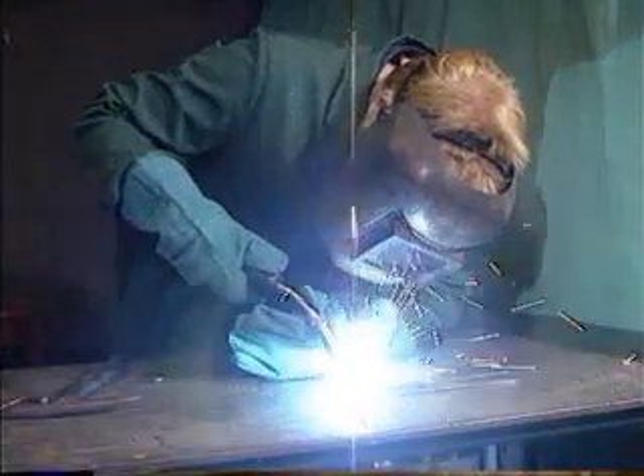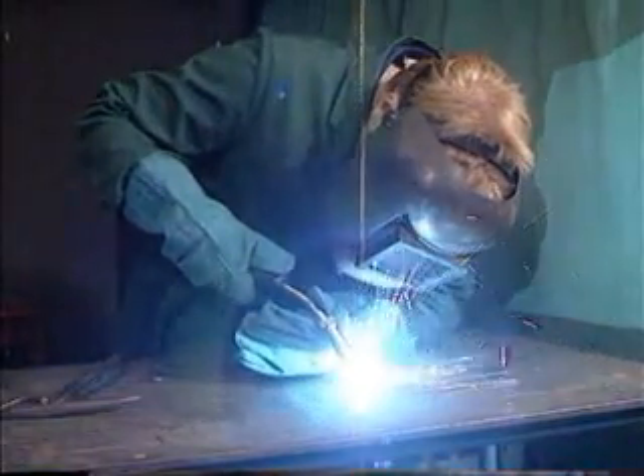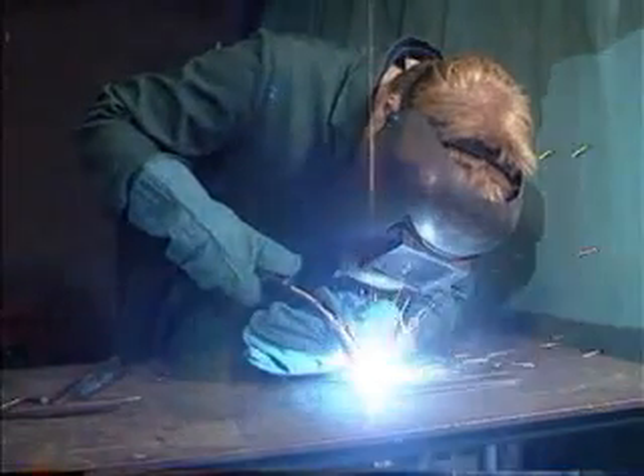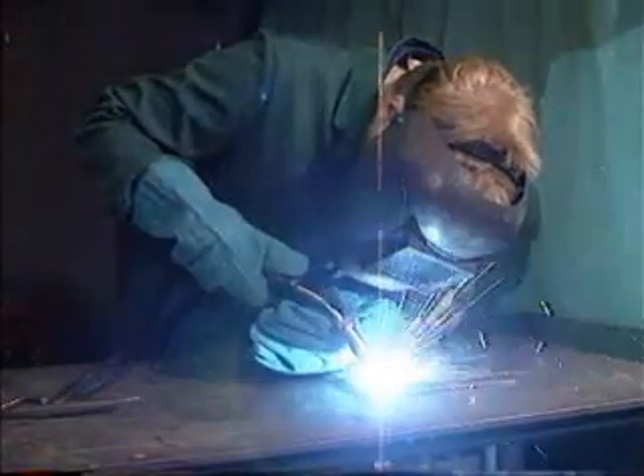In order to keep stable welding conditions with a low voltage arc, say 17 to 20 volts, which is being rapidly short-circuited, the power source must have the right characteristics. If the short-circuit current is low, the electrode will freeze to the plate when welding with low currents and voltages. However, if the short-circuit current is too high, a hole may be formed in the plate, or excessive spatter may occur due to scattering of the arc pool when the arc is re-established.